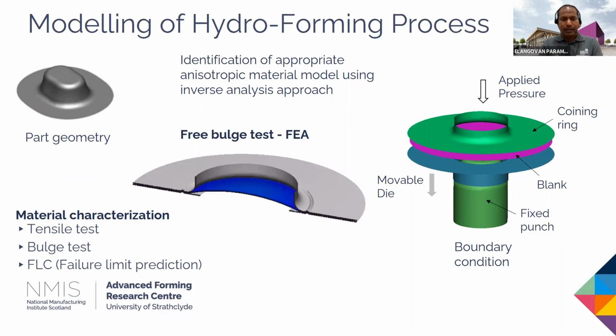This particular slide mainly focuses on the part geometry. This is the case study which I'm going to discuss now. So we have a part geometry. Before we go for the process modeling, we will try to understand more about the part requirements, for example, thickness, and any special feature requirements, for example, the top radius, the flange radius, etc. And before we go for the process model, we will analyze the material, as discussed in the previous section by Diego. We do a lot of material characterization for the benefit of accurately predicting the result. We do tensile testing mainly to characterize the work hardening behavior of the material and the anisotropic behavior of the material. And then we use the bulge test, mainly to capture the biaxial yield point, which is very critical to develop a material model.